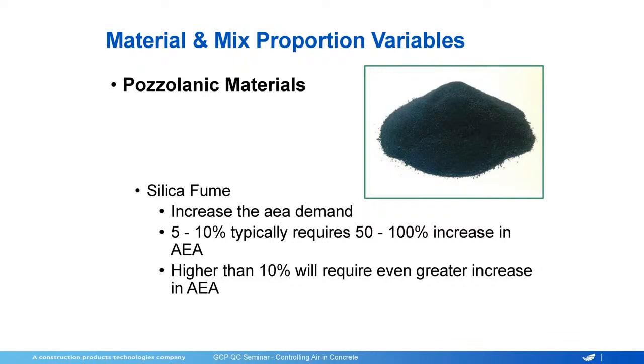Silica fume. Now, typically, it does cause your air entrainment dosage to go up. However, in some cases where you're using silica fume in a self-consolidating concrete mix, and you have a mix that is on the edge of segregation, so it's good. It's not segregating, but it's almost there. Those can be difficult to maintain air content. So you can get the air, but it comes out pretty quickly. And some of those mixes, if you use silica fume, it stabilizes that, stops that segregation, and actually will bring your air entrainment dosage down.